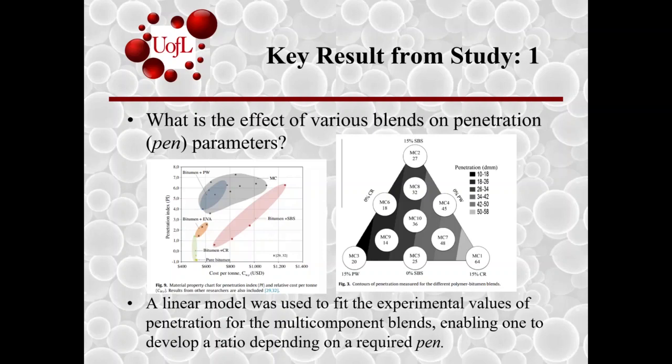One key result from the study was looking at what was the effect of various blends on penetration parameters. So for each of these 10 blends, they had evaluated penetration for the blend itself. And from their experimental values, they had created an equation. They used a linear model to fit the experimental values of penetration so that one could develop a ratio depending on the required penetration parameters they have in mind.